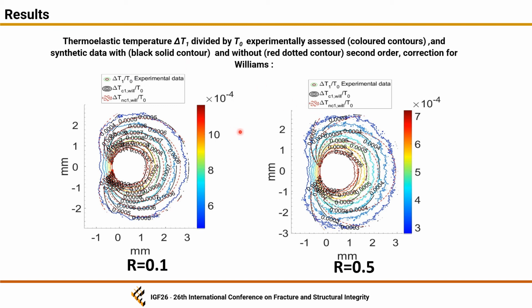Even in this case, referring to this comparison of experimental data and synthetic data obtained by using the Williams series expansion, we can see that the new formulation, represented by the black solid contour, which takes into account the mean stress effect, approximates the experimental data very well, and the same consideration can also be drawn for the 0.5 stress ratio.